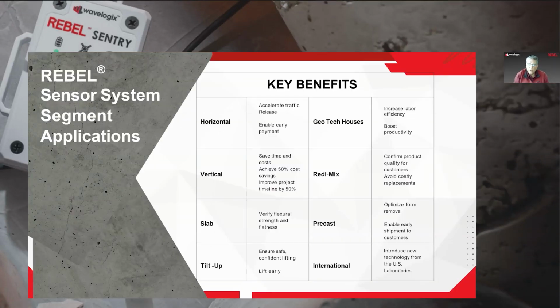Benefits of knowing strength in real time. If you look at horizontal, we can accelerate traffic release. We can enable early payment if you've hit the structures. A lot of horizontal work is paid when you reach the specified strength, so if you know when you've reached that strength, you can get paid. Vertical, we believe that our sensor system can save contractors about 50% of the cost of doing cylinder breaks. In slabs, along with the temperature that we produce, you could verify the flexural strength. We also present our data not only in compressive strength but also in flexural strength. So using our sensor system with a slab gives someone some great benefits to knowing what that flexural strength is.